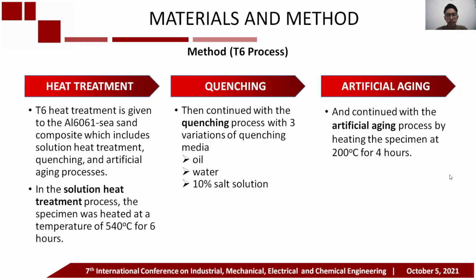The heat treatment method is T6, consisting of solution heat treatment, quenching, and artificial aging processes. In the solution heat treatment process, the specimen was heated at a temperature of 540 degrees Celsius for 6 hours. Then continued with the quenching process with three variations of quenching media, namely oil, water, and 10% salt solution, and continued with the artificial aging process by heating the specimen at 200 degrees Celsius for 4 hours.